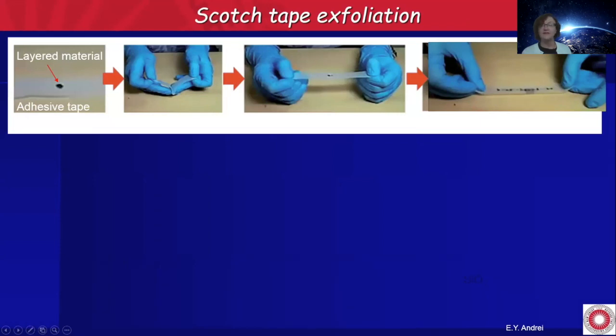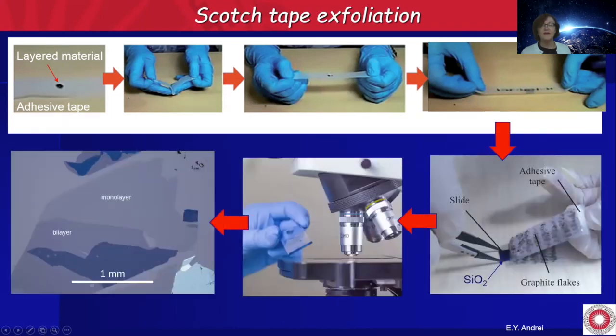They took graphite, picked it up with a piece of Scotch tape, then brought the Scotch tape together and opened it up. So you have two pieces, and you repeat the process many, many times. You end up with 4, 16, 32, and so forth, and you end up with many very thin flakes, which you can next take and look at under the microscope. You put it on a substrate here.